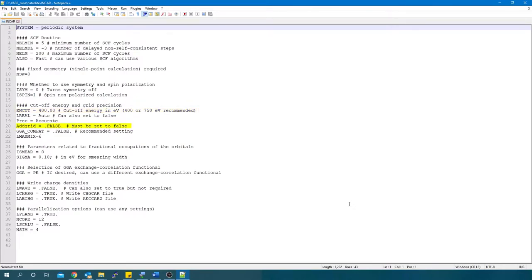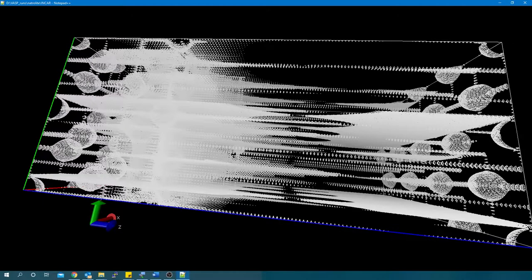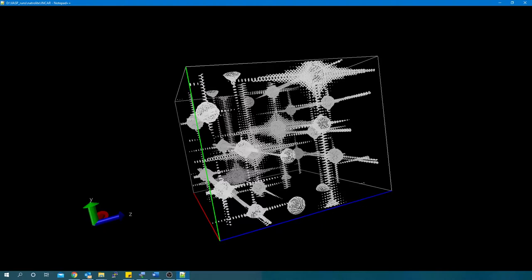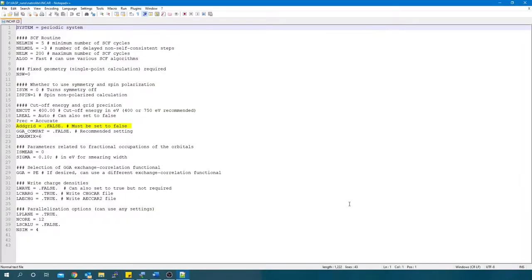ADDGRID equals false. If set to true, this keyword adds an additional support grid for the augmentation charges compared to the standard fine grid. However, these extra support points introduce aliasing, aka, wrap-around errors, that make the electron density oscillate. In this figure, we can see a plot of the core density. Instead of having rounded spheres, spike-like atoms are observed due to density oscillations when using ADDGRID equals true, and will not occur with ADDGRID equals false. The CHARGEMOL results for the calculation setting this keyword to true do not give good sound results. Therefore, this keyword must always be set to false.